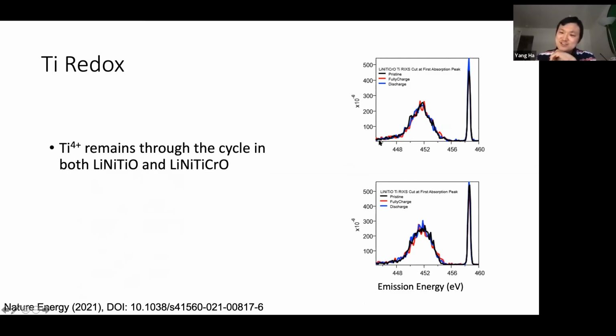Oh, I also need to mention that for this kind of emission measurement, you can open up the slits, and each emission will take only 1 minute or so. So the total experiment is like a 10 or 15 minute measurement. You probably spend more time moving your sample around than on the real measurement. So it's actually even faster than the traditional X-ray absorption. So just keep your mind active. With the RIXS capability, you really have a lot of things to do.